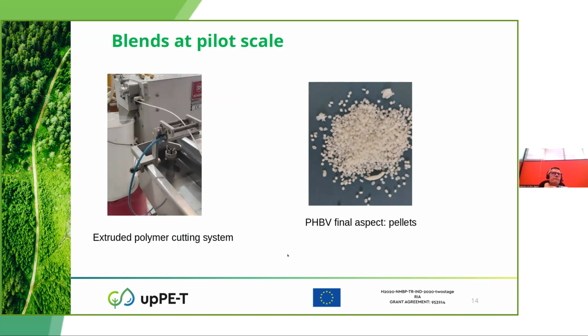Finally, you can see here how we get with the homogenization process in the twin screw extruder. The strand exiting the extruder is cut by a pelletizer, producing pellets. The pellets you can see on the right. This is the PHBV final aspect of the pellets.